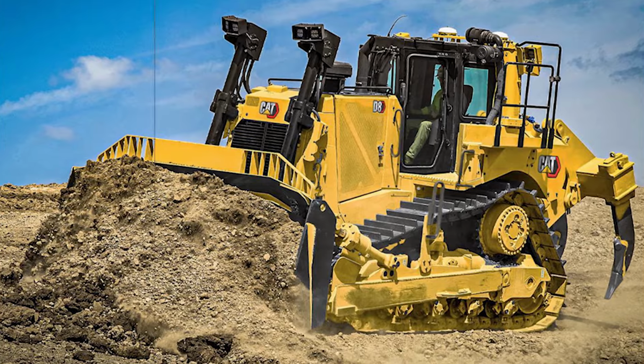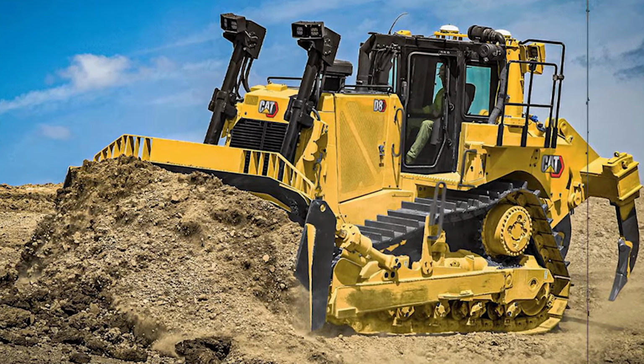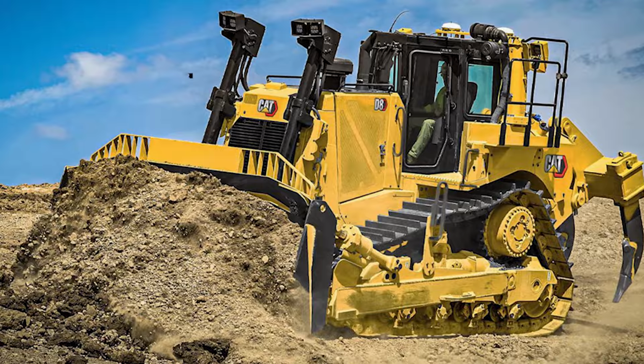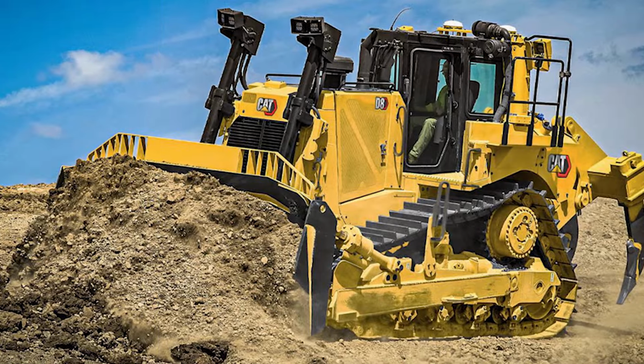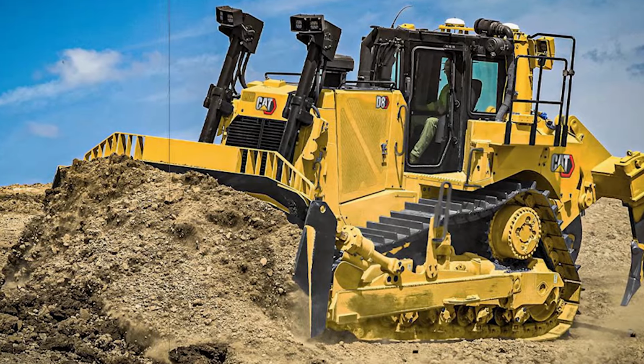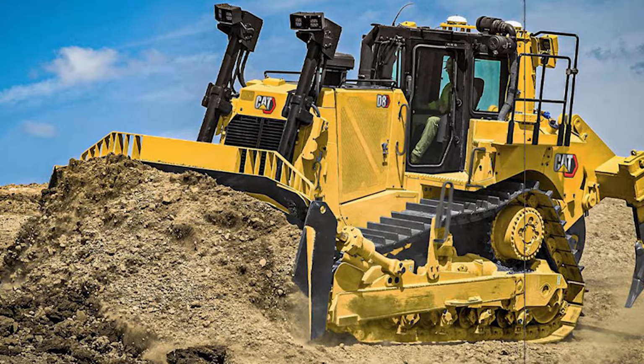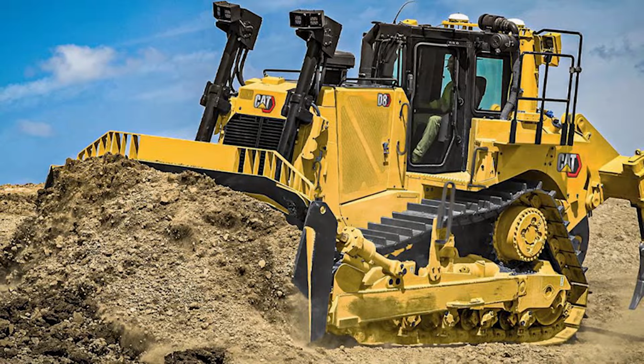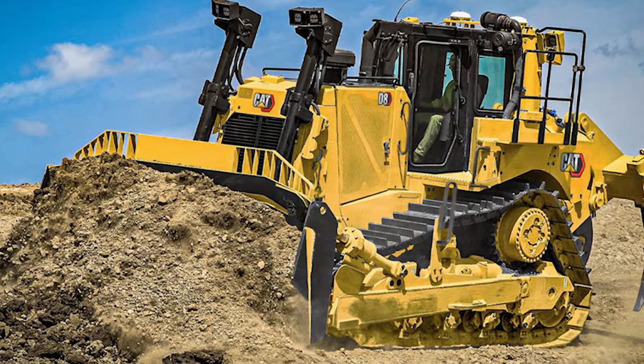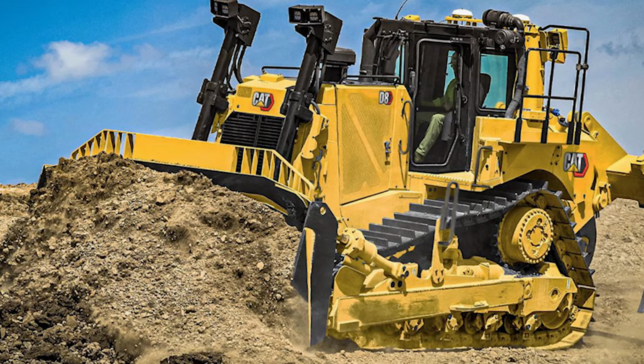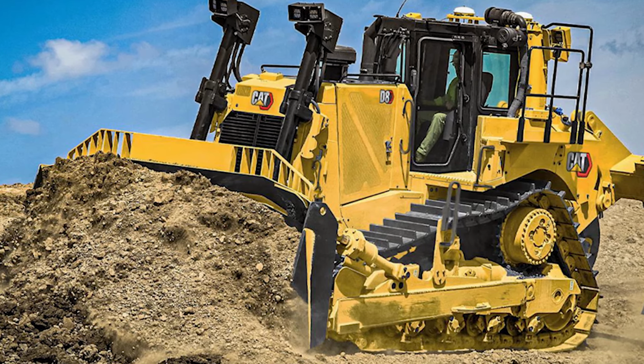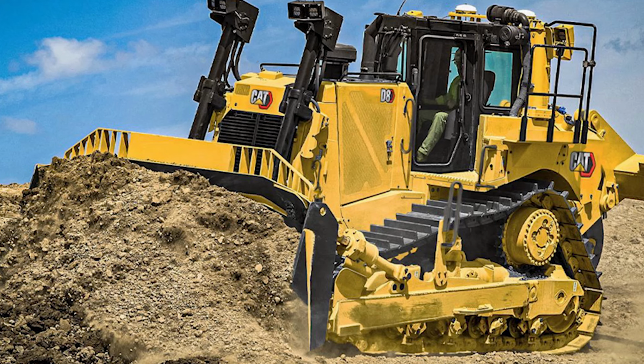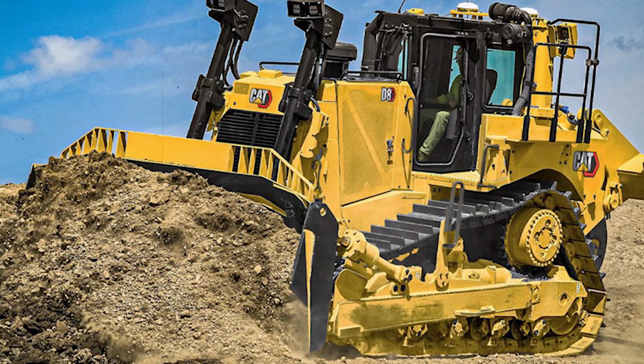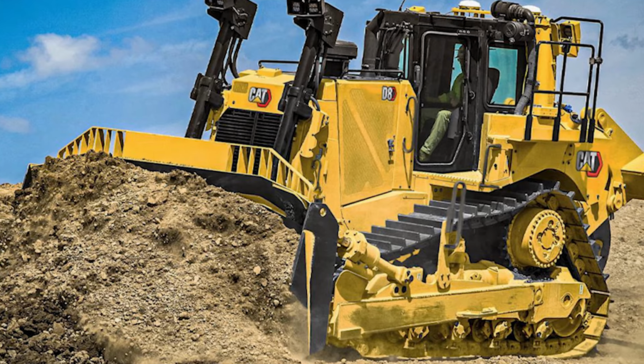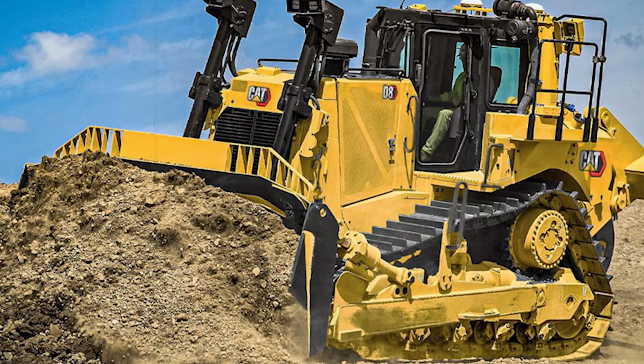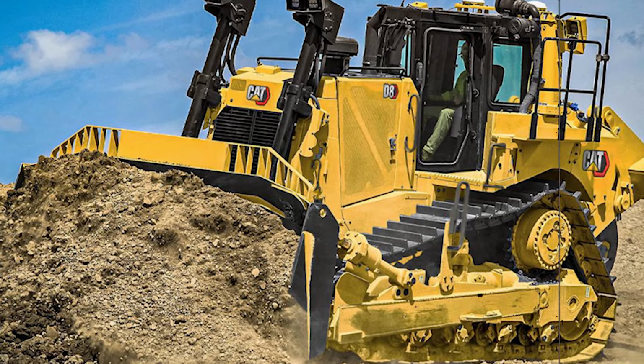By the second week of operations, blade edges had reached 320 Brinell hardness, surpassing the original strength of conventional carbon steel through punishment rather than despite it. The transformation accelerated as operational hours accumulated, and impact forces continued reshaping the manganese steel's crystalline structure. 200 hours into the testing program, blade edges measured 380 Brinell hardness while maintaining sharp cutting geometry that conventional blades had lost through predictable wear patterns.